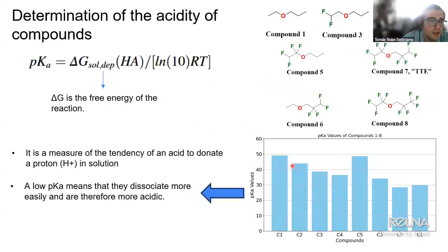the adsorption energy. Another calculation that we can do to understand this is the pKa. The pKa is a measure of the acidity of the compound. In this case, the acidity represents a measure of the tendency of the compound to donate a proton, or in this case, the electron attached to the compound. And as you can see here, lower values of the pKa mean they dissociate more easily. So you can see that there is more or less a trend that decreases the pKa as you increase the fluorination of the compound.